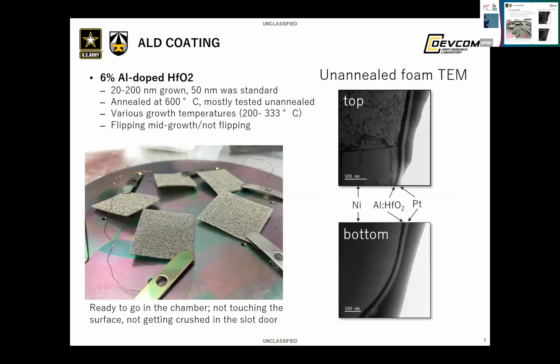The composition that we did was 6% alumina-doped hafnia, and this is a composition that was developed with a student that Jacob Jones and I were co-advising. We settled on this at ARL as our token energy storage composition. We grew films from 20 to 200 nanometers, but most of what we'll talk about today is between 50 and 80. We did successfully anneal them, but most of what we tested was unannealed because we were scared about them cracking or having them touch any other surfaces.